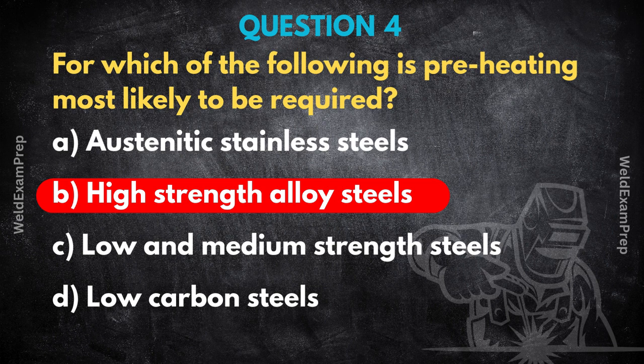So preheating is kind of like a metallurgical slow cooker. That's a perfect analogy. By warming up the base metal first, you dramatically slow down that cooling rate. Which gives the microstructure time to form into something less brittle. Exactly, something more ductile. And just as importantly, the heat helps any trapped hydrogen to diffuse out of the weld before it can cause any trouble.